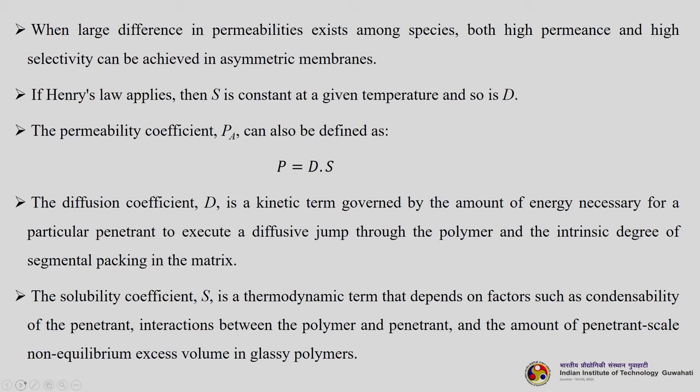If Henry's law applies, then S is constant at a given temperature, and so is D. The permeability coefficient is also defined as P equals D S. D is the diffusion coefficient, a kinetic term governed by the amount of energy necessary for a particular penetrant to execute a diffusive jump through the polymer, and the intrinsic degree of segmental packing in the matrix. The solubility coefficient S is a thermodynamic term. So, D is a kinetic term, whereas S is a thermodynamic term that depends on factors such as condensability of the penetrant, interactions between the polymer and penetrant, and the amount of penetrant in the non-equilibrium excess volume in glassy polymers.